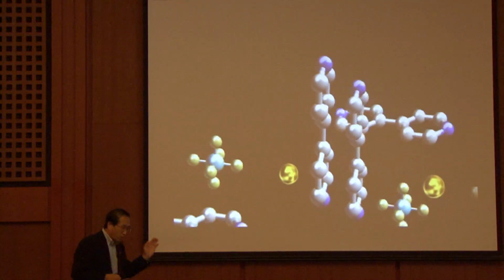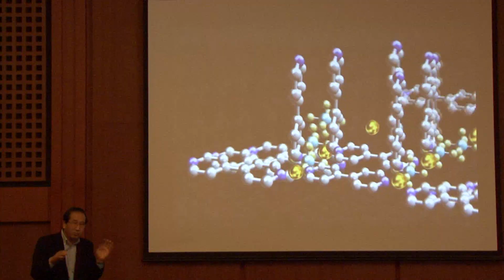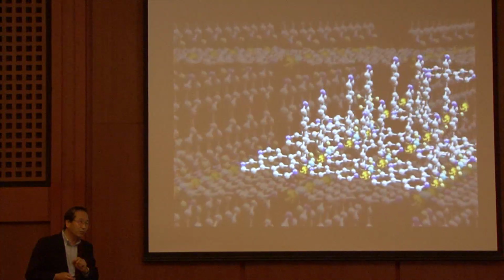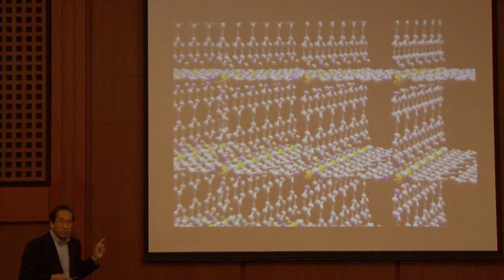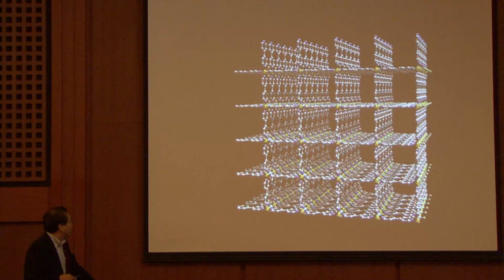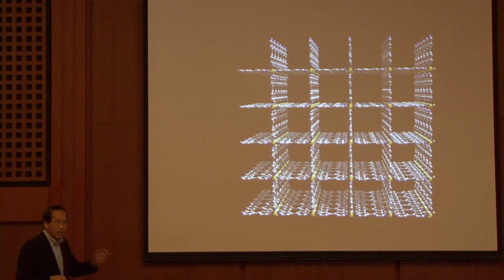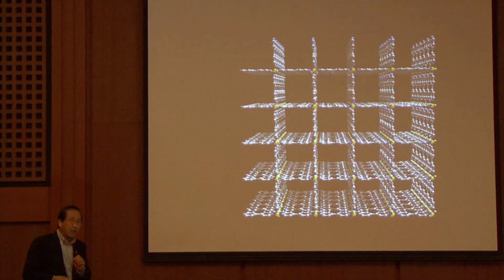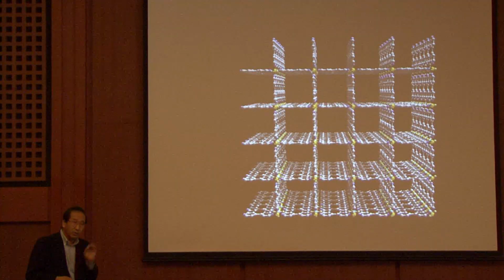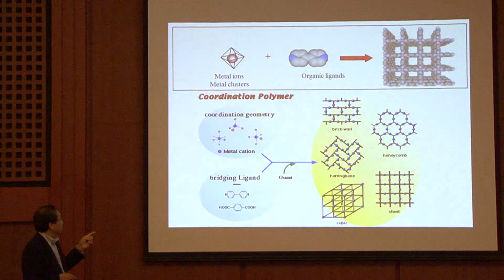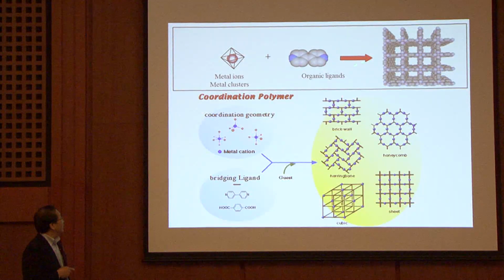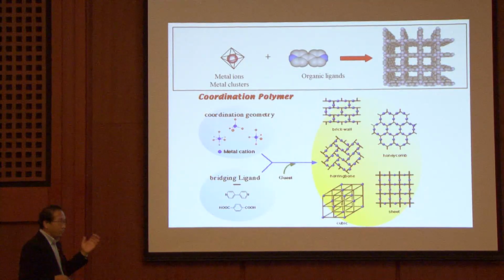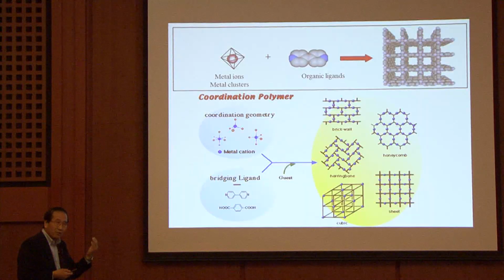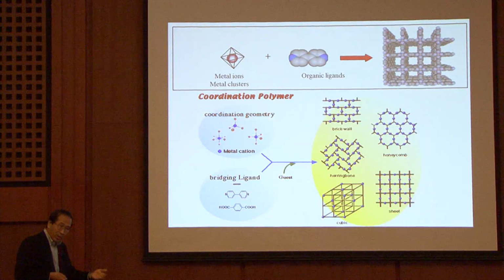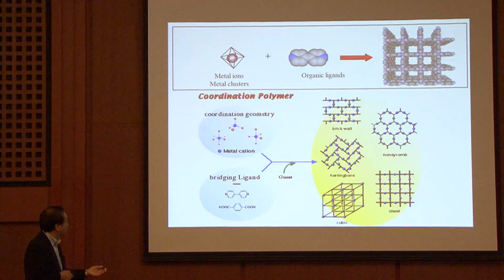By using this, you have the organic ligands and metal ions in the flask mixed at room temperature at ambient pressure. In a minute, you can get this kind of framework. That is the micron crystalline materials. The size around 1 micron to 500 microns, very small. But you can get this. This is just the assembly process. And in the macro scale, we have the block game and Lego. But in the nanoscale, we carry out this kind of chemistry.